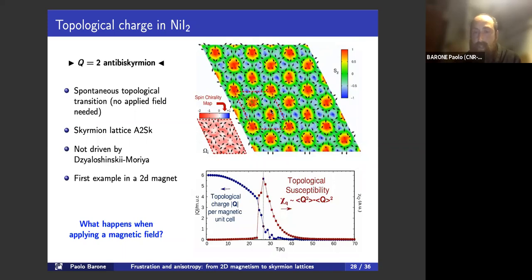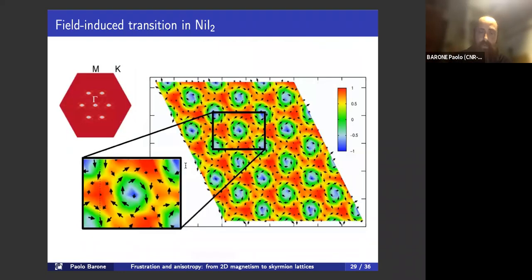So the basic periodic unit of our magnetic structure, which is shown here by this rhombus, actually contains 2 cores. So we are really looking at an anti-skyrmion lattice. Even more interesting, this is a spontaneous transition. So there is no magnetic field in the model, and there is no Dzyaloshinskii-Moriya interaction. The only anisotropic terms here are the easy-plane single ion anisotropy and the exchange anisotropy.